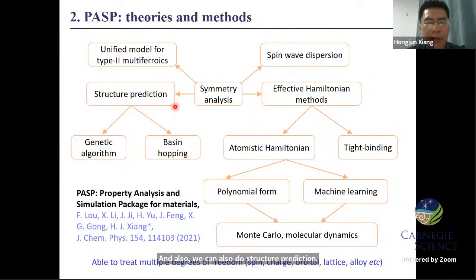For example, we can predict the distortion of perovskite structures, including rotational and also ferroelectric distortions. And we have different kinds of optimization techniques. For magnetic systems, we can also compute the spin wave dispersions. Another important part in our package is the effective Hamiltonian methods. We include the tight binding model for electronic degrees of freedom, and also the atomistic Hamiltonian for atomic displacement and also spin degrees of freedom.